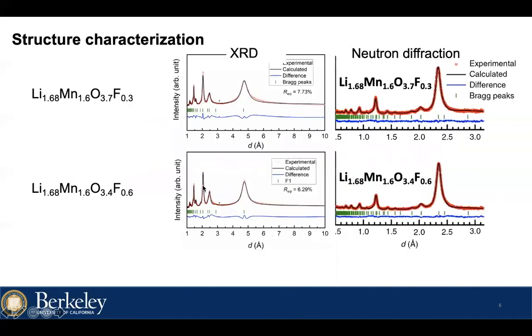Following these two strategies, we have synthesized this compound by mechanical ball milling. Another sample with an even higher fluorination level was synthesized to further increase the manganese redox. To characterize the structure, we did synchrotron XRD and neutron diffraction. The diffraction data showed both materials adopt a spinel-like structure.